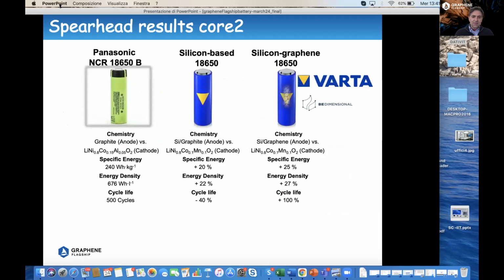And one of the activities related to the Spearhead, we had in the core 2 a Spearhead led by Varta, targeting the production of a battery using a silicon graphene composite as anodic material. And the Spearhead project was quite successful. You can see here what has been achieved using silicon graphene compared to silicon graphite.